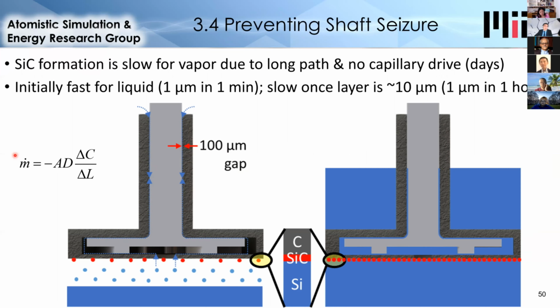And so if we estimate how long this would take based on mass transfer, it would take about 3 days for a 10 micron layer of silicon carbide to form. So essentially in these experiments, no silicon carbide layer formed via vapor coating. So we know we're gonna have to lower the punch into the silicon to cause this reaction.